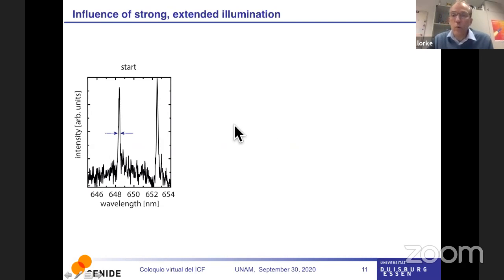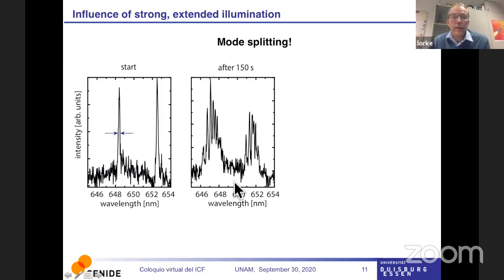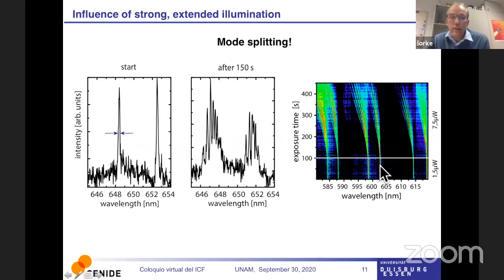And then he noticed something quite peculiar, really strange. Because when he started this experiment, he had seen the spectrum that I had just shown you. And after some minutes with heavy illumination, he saw that this mode started to split. And when he took a cut at one time, he saw these nice, sharp, double resonances that I had been talking about. And if he did it for a while at low laser excitation, nothing much happened. And if he turned up the laser excitation, he saw this splitting, and it looks very, very regular.